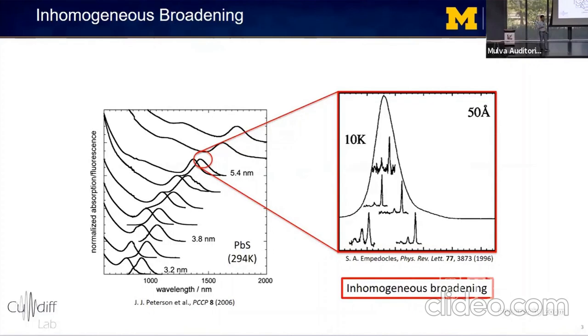So this gives you an idea for some of the difficulties with studying the optical properties of these nanocrystals, since in an ensemble, you just get these broad line shapes that only give you information about the size distribution of the ensemble, while the fluorescence spectra of individual nanocrystals varies dramatically even within the same batch of nanocrystals. And if you want to design a device using these nanocrystals, you want to know about their ensemble average properties, since you don't want to design a device around the properties of a single exceptionally good or exceptionally bad nanocrystal.